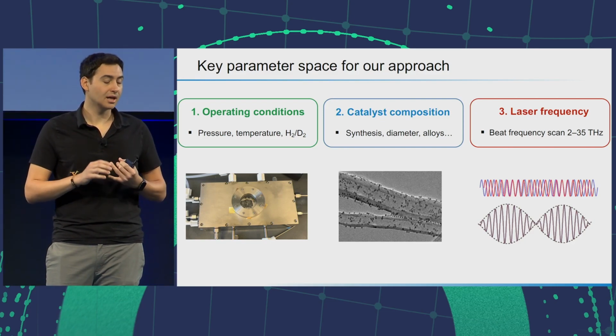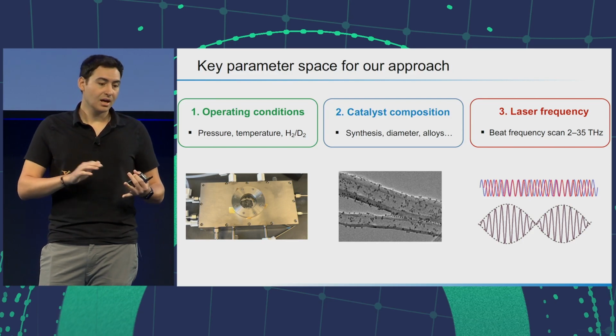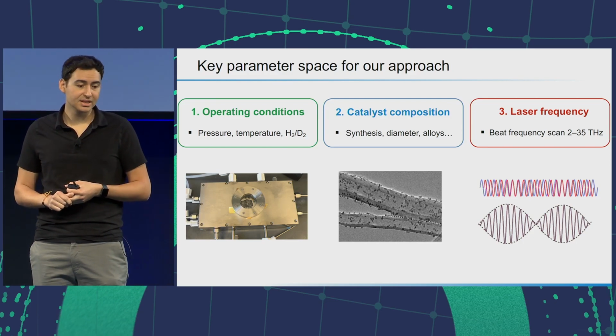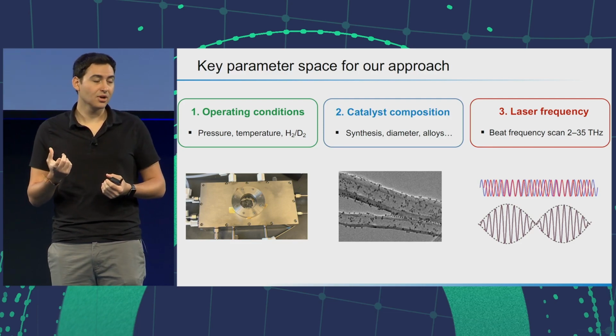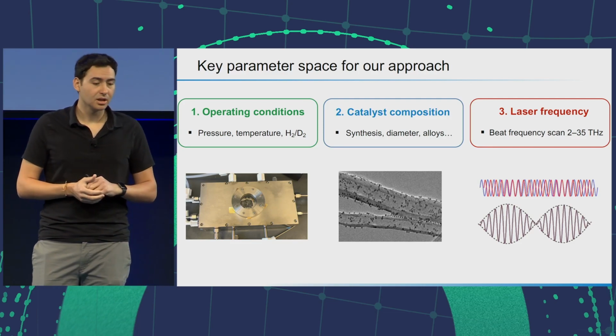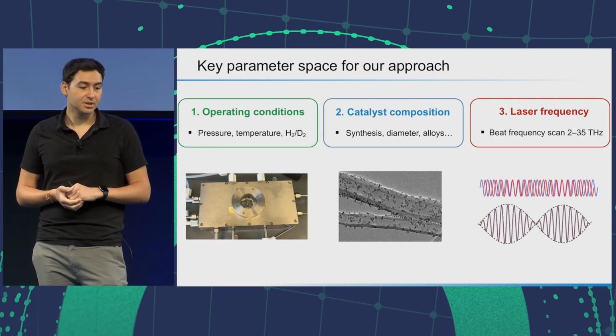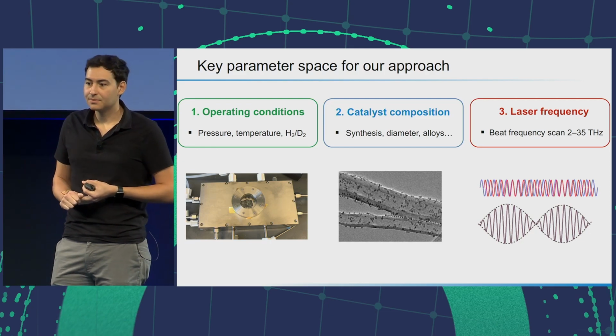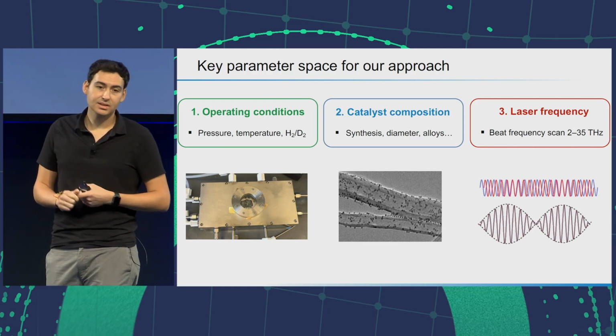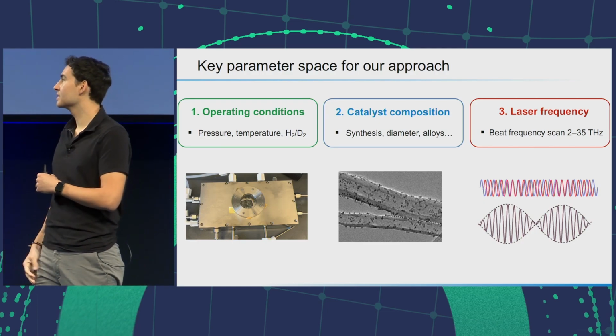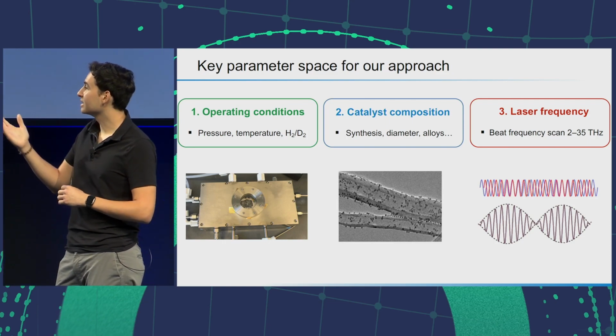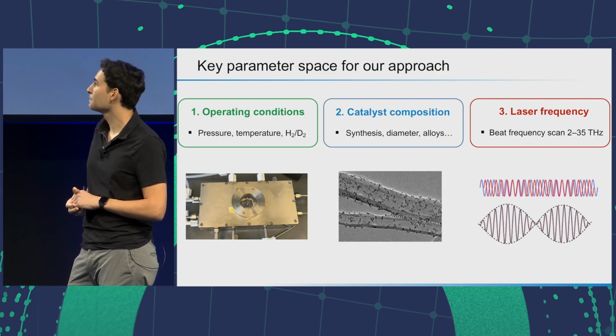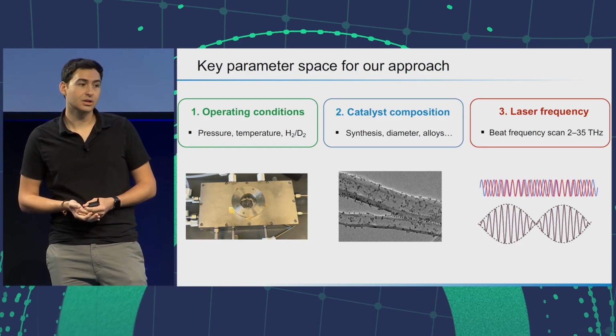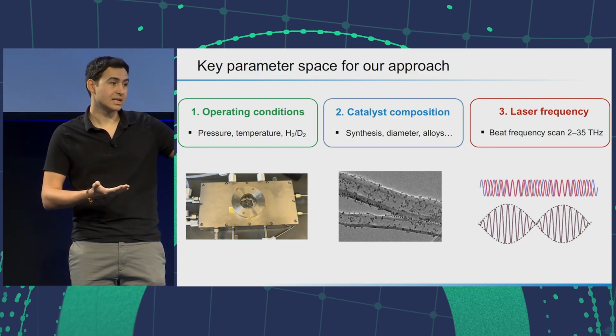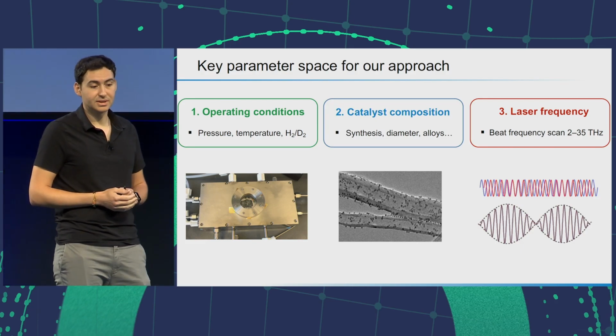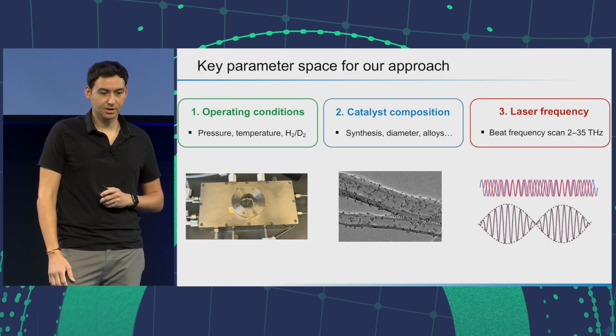One is what the reactor is doing, so that's operating conditions. Pressure, we could go up to about 10 bar, 500 Celsius, and we could tune the hydrogen-deuterium ratio, which I think is at least something that I thought was a new component, tuning that smoothly between 0 and 1. A second is the catalyst composition, which we think is our specialty. Different synthesis approaches, controlling the diameter, the alloy composition, size, shape, what have you, the density of nanoparticles on the nanotube, for example. And lastly, the stimulation source, so laser frequency, scanning over these different terahertz frequencies to try and generate that beat frequency. So those are the 3 buckets we would like to explore.